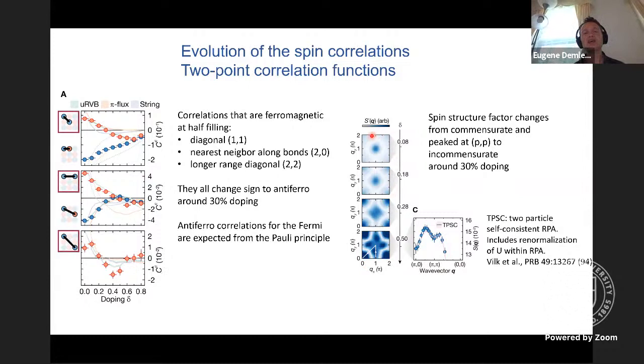Then we can also take these real space images of correlation functions and convert them to momentum space correlation functions, which is what we're used to from neutron scattering. And we see that at the same doping, the nature of correlation changes from one which has a single peak at pi to something that has split peaks, and that's called incommensurate spin fluctuations.